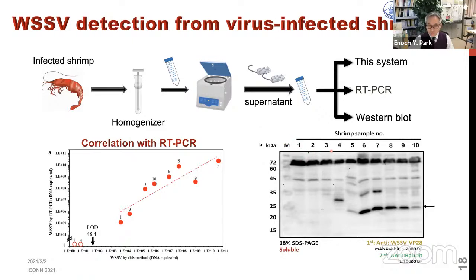From 1, 2, 3, 4, here is the VP28 protein band. However, we cannot confirm this band in samples 1, 2, 3, 4. And from 5 to 10, we can exactly confirm the very thick VP28 protein band. Therefore, we think samples 5 to 10 are possibly WSSV infected. And samples 1 to 4 are negative for WSSV infection. Therefore, we can very easily detect positive or negative WSSV infection in real shrimp.